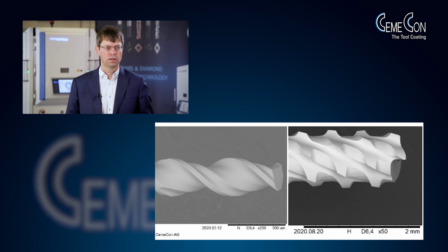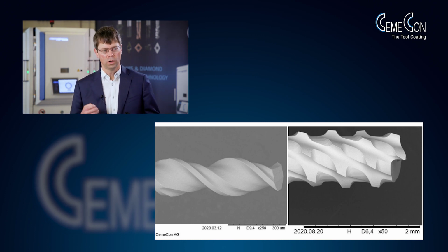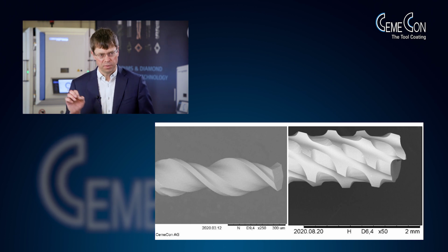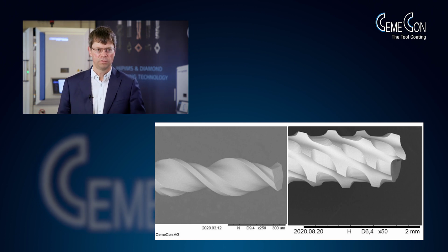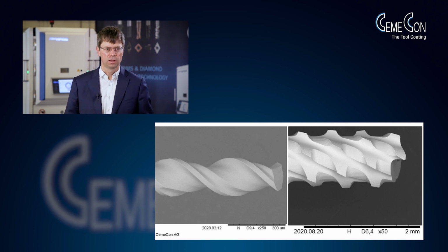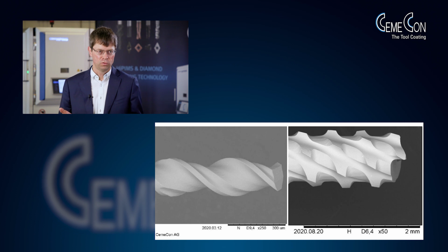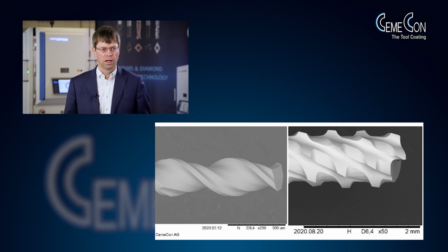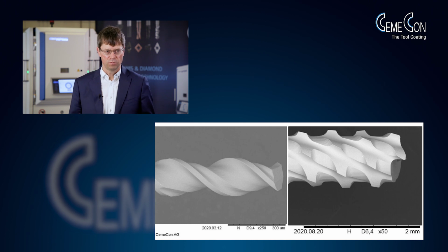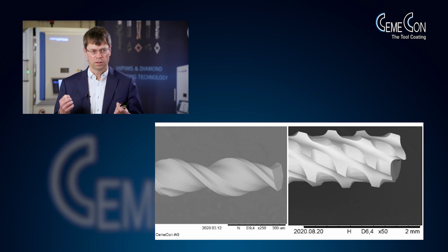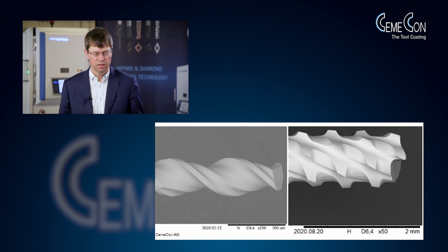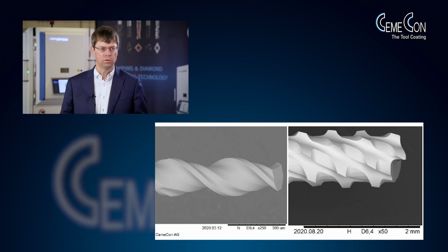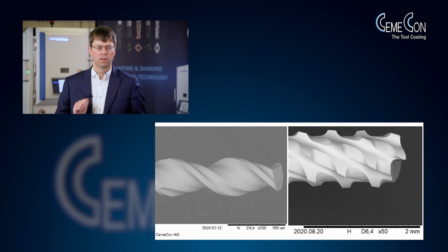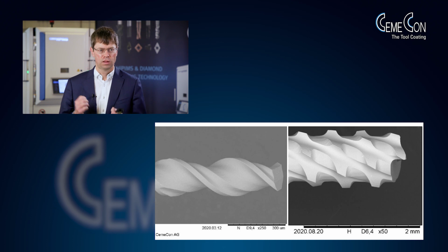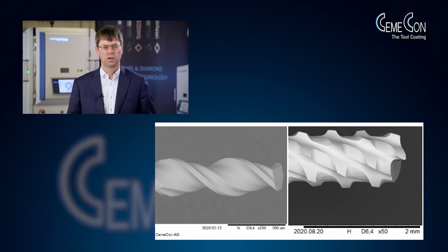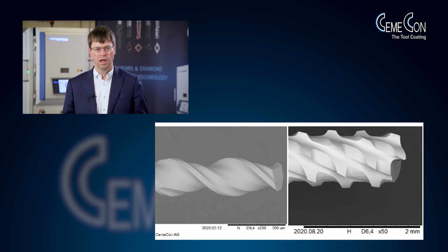The other example on the right-hand side is even more striking. It shows a router tool for shaping printed circuit boards, for example, for your telephone or for such a presenter, the electronics. A very sharp geometry, very much looking like a wood machining tool. Here, it's clearly visible from the geometry that the coating must be very tough, very dense, and you must find a way to bring down intrinsic stress to cover such a sharp geometry homogeneously. And stress management, that's a fully new thing, what you can do by tailoring the HiPIMS pulses in the right way.